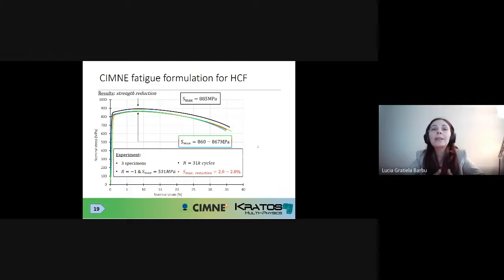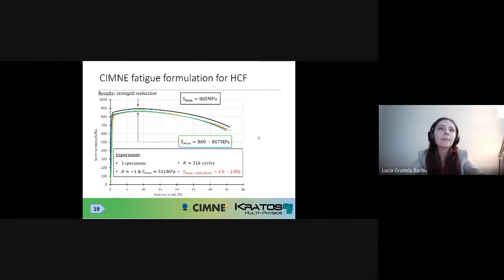What they saw experimentally was that there was a reduction in the maximum stress achieved inside the specimen of about 2%, 2.8%. Basically, the maximum level of stress went down from 885 megapascals to about 865, let's say, as an average.